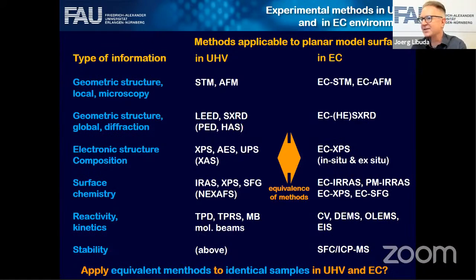I probably give the same answer every time you ask me that. Again, I think that depends very much on the system that you're looking at. We also have, let's say, limited experience with electrochemical STM. We're using it for a few years now on these complex surfaces. I think the problem is the potential control on the tip. You cannot just play with the potential on the tip as you like. The degree to what you can do that depends very much on the conditions.